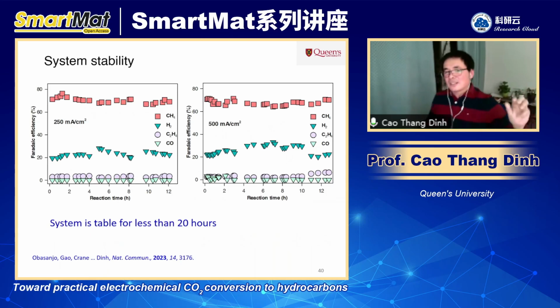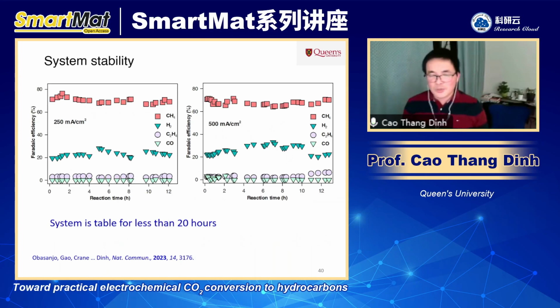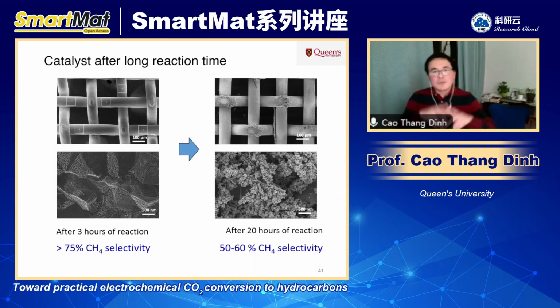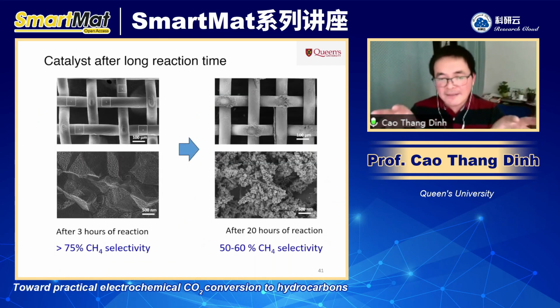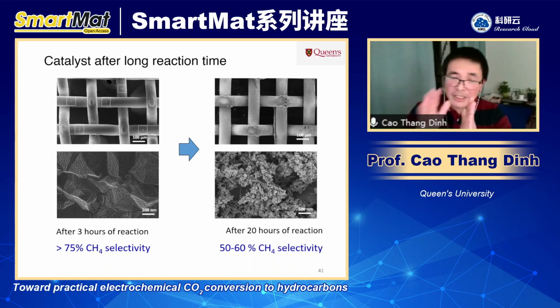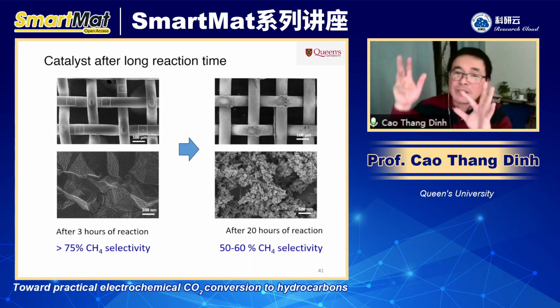So what is going on here? Our group is focused on the stability, right? So we are not satisfied with the reaction running less than 100 hours. We try to understand what is going on here. So when we look at the substrate after a very long reaction, like after 20 hours, by that time the methane started to decrease to about 50, 60%. And at the same time, ethylene increased.